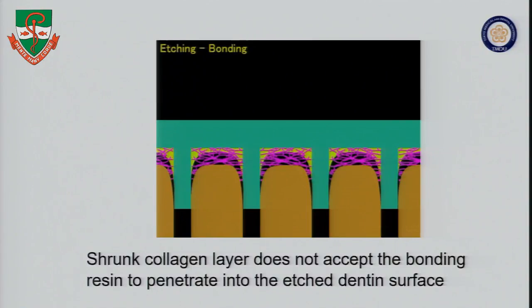After the light curing, of course, we could observe the hybrid layer formation. However, at the bottom of the hybrid layer, there is just the layer of collagen without penetration of the bonding resin. That's why this space becomes the weak point at the bonding interface afterwards.